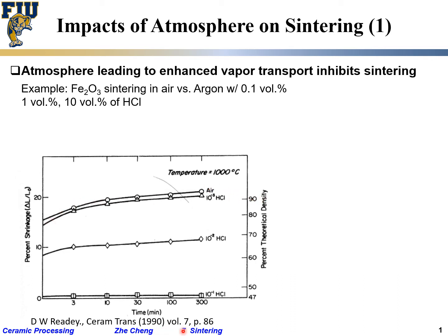percentage density versus time reaching the same temperature. So we are doing temperature, time, the so-called isothermal sintering. Make sense? We reach this temperature and then hold for different times. If we are doing it in air, you see, okay, it starts from this one, 80, higher. Why? Because before reaching here, during the heating up stage, my sample already got partially sintered. Make sense? That's why it starts not from 50, but from 70, 80. This is during the heating up stage, it's already been partially sintered.